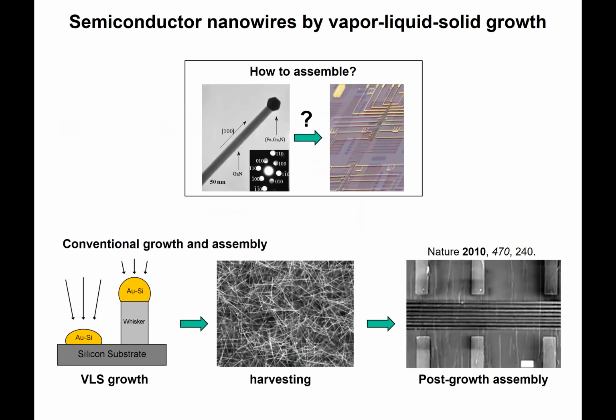Now, one of the big problems of using nanowires in technology is that, okay, you can grow very nice nanowires, but normally they grow as a forest. So they grow, for instance, in the vapor-liquid-solid growth mechanism from nanoparticle seeds, where the material comes from the vapor, dissolves into the nanoparticle, and grows as a wire.